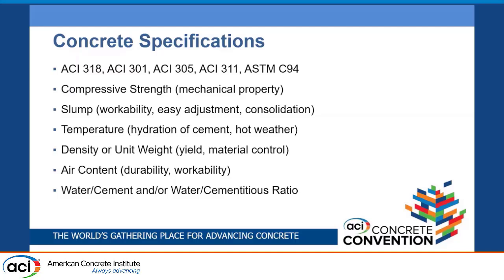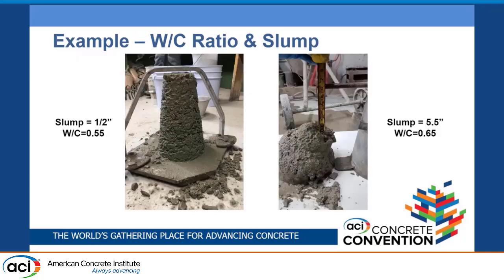Density or unit weight of the concrete, so we know that we are inside of that required yield. Air content for durability and workability, and the water cement or water cementitious ratios. We need to know what water cement ratio we need, what kind of slump we have. Because sometimes we have specifications or drawing plans that request 3 inches of slump for a wall. But we know that in a wall that could be 6 inches of thickness, a concrete with a 3-inch slump is not going to be that easy to pour. So we need to manage that information, what kind of admixture we are going to use to make it more fluid to go inside of the formwork.